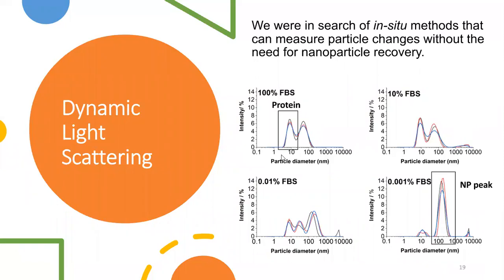And what we can see between neat serum and a 1 in 10 dilution is that actually very little changes. We start to see something here, but it's not until we get to a really, really low concentration of fetal bovine serum that we resolve the two clear peaks that we wanted. But this particular concentration of fetal bovine serum is so far removed from physiological conditions that any data that we do get isn't really biologically relevant. And we see much the same thing if we then choose to look at the volume distribution of these same samples.